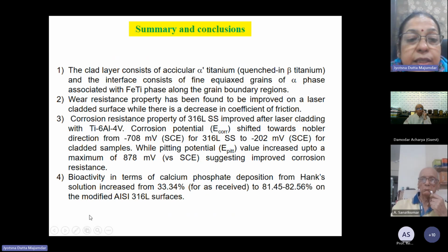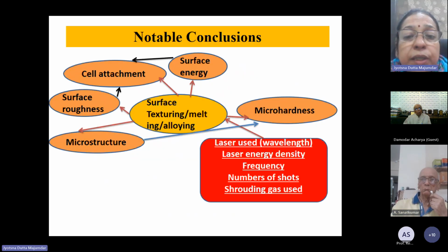So this is also a very interesting way of designing an implant by combining two materials. The core is cheap and formable, because AISI 316 stainless steel is highly formable, weldable, and also cheaper compared to Ti6Al4V. If you have a Ti6Al4V surface and an AISI 316 stainless steel core, that would obviously give a very good economic way of having very good implant materials.